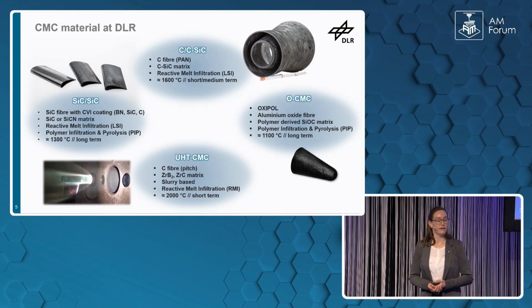Another CMC class are oxide CMCs based on aluminum oxide fibers. In our department at DLR, we combine them with a polymer-derived silicon oxycarbide matrix for temperatures around 1100 degrees C in long-term use.